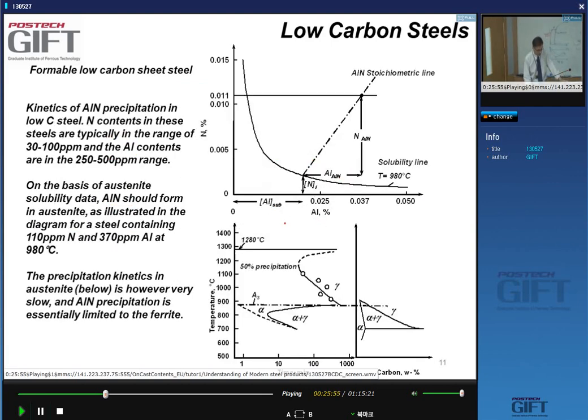The aluminum and the nitrogen play a very big role in these low carbon steels, and in particular, the precipitation of aluminum nitride. The nitrogen is less than 100 ppm, typically 40 ppm, and the aluminum, as I said, 300 to 500 ppm, or 300 to 400 is more exact.